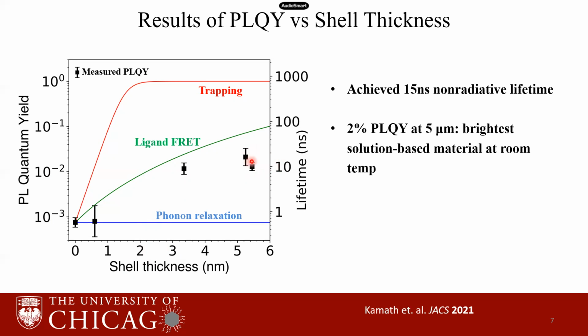For the thickest samples, the PL quantum yield is 2%. And this is the brightest quantum yield for any material in solution at this wavelength at room temperature. So this shows that these quantum dots are excellent materials for making efficient mid-infrared LEDs.